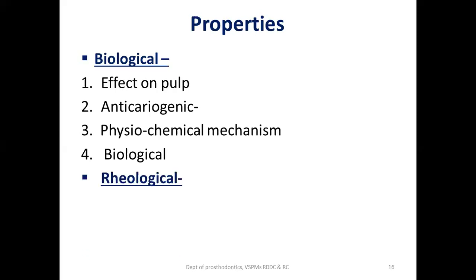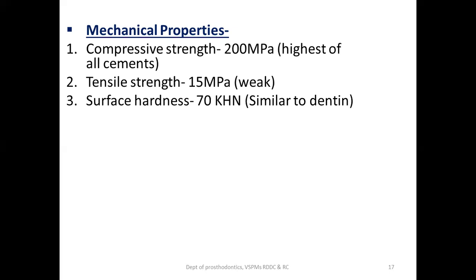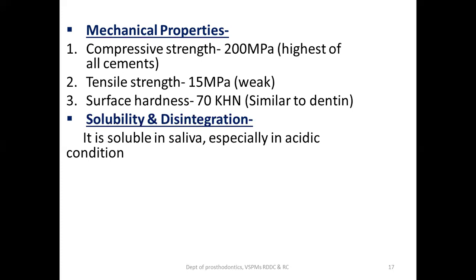The second property is the rheological property. The mixing time is 45 seconds to 1 minute. The setting time is around 3 to 8 minutes. In mechanical properties, the compressive strength is high, 200 MPa. Tensile strength is less, 15 MPa. The surface hardness is similar to dentine, that is 70 hardness number. It is soluble in saliva, especially in acidic conditions.